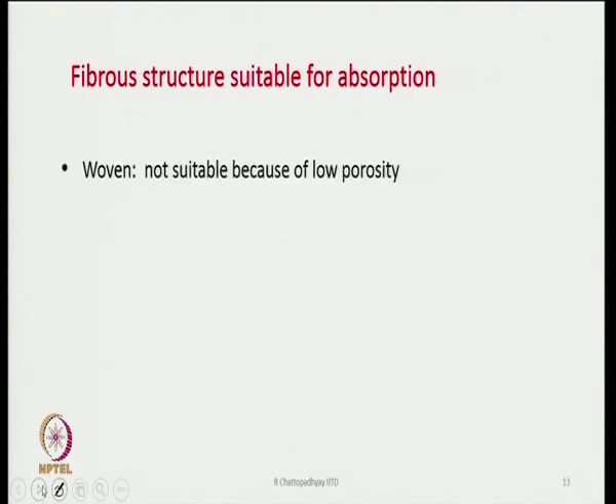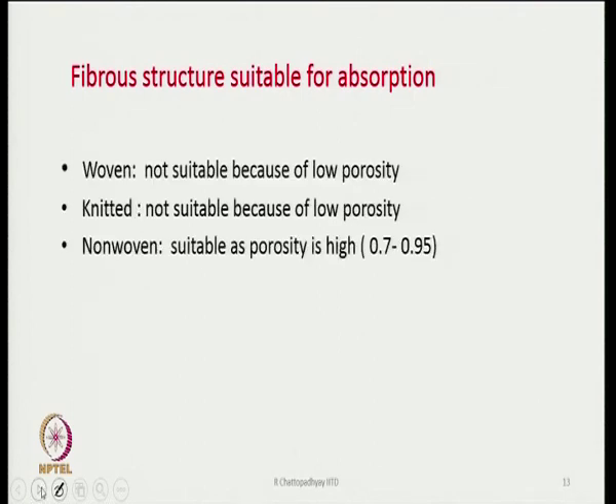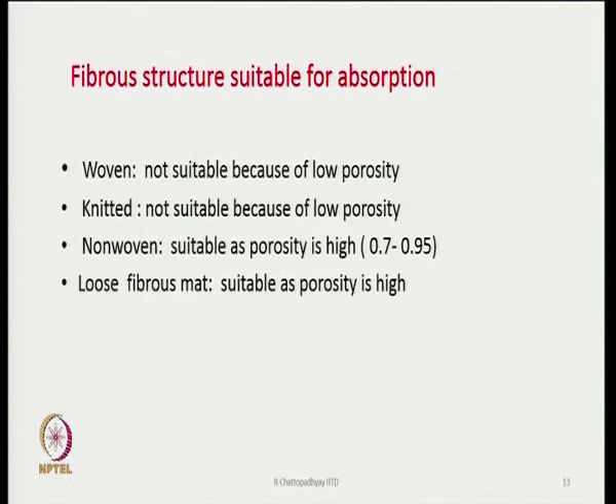Fibrous structure suitable for absorption, which I have already discussed: woven is not suitable because of low porosity. Knitted is also not suitable because of low porosity. Nonwoven is suitable because porosity is high. Typically, nonwovens will have porosity 0.7 to 0.95. This we can study from the literature, that commercial nonwovens which are available can have porosity values from 0.7 to 0.95. 0.95 is a very porous structure, 0.7 is quite tight structured.